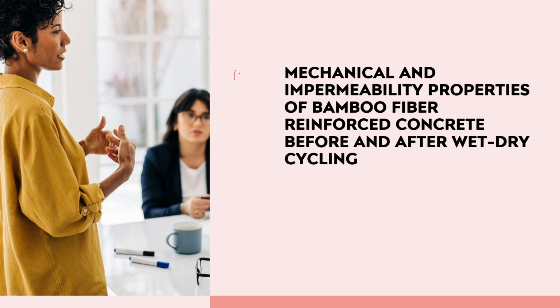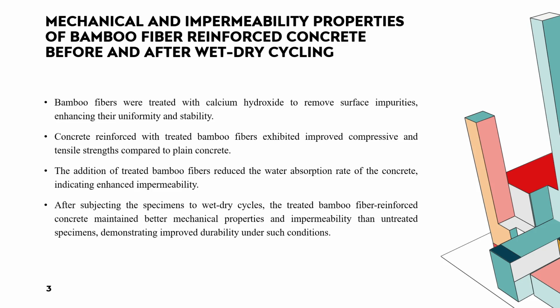First is mechanical and impermeability properties of bamboo fiber reinforced concrete before and after wet and dry cycling. In this paper, they used bamboo fiber and treated it with calcium hydroxide, Ca(OH)2, to remove surface impurities, enhancing uniformity and stability. The results are that concrete reinforced with treated bamboo fiber exhibited improved compressive and tensile strength compared to plain concrete. So results are good.